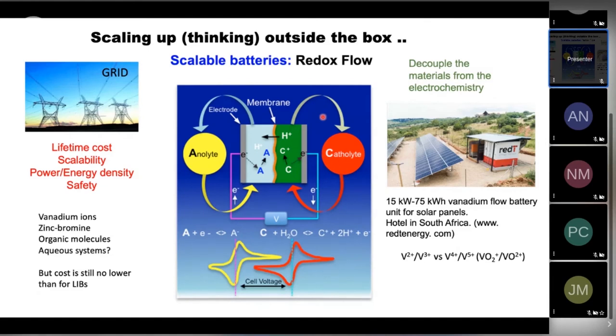So I just want to end with an idea which I think will be interesting to many of the chemists in the audience, about how we scale up and how we decouple the materials from the electrochemistry. And the way that one could think about doing this is to use a so-called redox flow battery, where you have vats of reduced and vats of oxidized materials, and you flow them in when you want to do electrochemistry. And these systems are similar to fuel cells, except they're reversible. So you can both generate power, and then you can turn the system the other way around and recharge your battery. Now, the semi-commercial systems are based on vanadium, where on one side you've got a vanadium 2+/3+ couple, and the other side you've got a vanadium 4+/5+ couple.